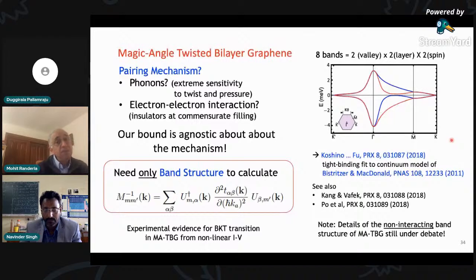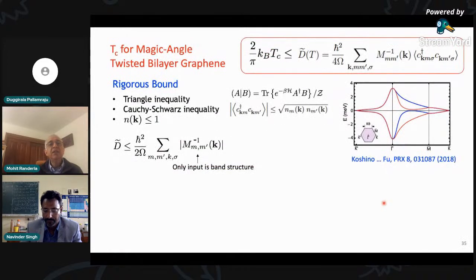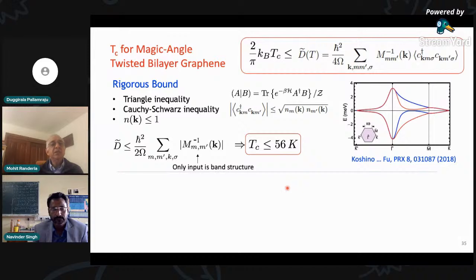So the band structure is complicated here. You have 8 bands, 2 valleys, 2 layers, 2 spins. And some details of the non-interacting band structure are still under debate. But here I use the Koshino-Fu tight binding fit to the continuum model of Bistritzer and MacDonald. And then first I go through a rigorous set of inequalities, which I will not go into. Triangle inequalities, Cauchy-Schwarz, by introducing an inner product in the space of operators. And the rigorous answer is that TC cannot be more than 56 Kelvin, just based on band structure alone and nothing else.